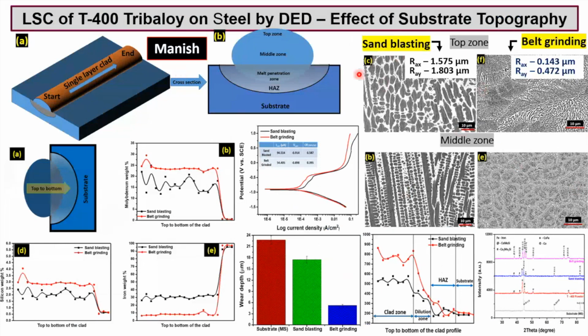Another student, Manish, showed that when you deposit onto the surface, morphology and surface condition play a role. Without telling you much, if I simply show you these two sets of micrographs, you can easily make out they're the same material. The clad material is the same composition, same operation, but with two different surfaces, one with prior sandblasting, one with prior belt grinding. And in the process, you can develop such different kinds of microstructures. You can very well imagine then the properties also will vary significantly.